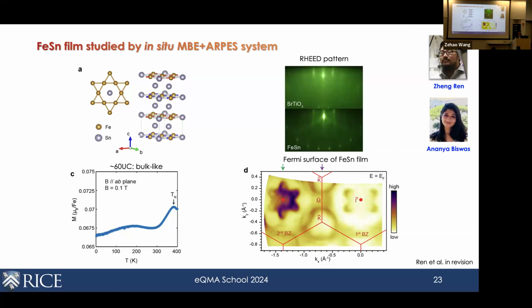So the really interesting or nice thing about this is that it turns out these thin films are very robust. They can live in vacuum for like a week, and you can still measure and everything is reproduced. And it's very robust also to thermal cycling. You can go across this TN and then come back down. And then to our delight, all of the features remain, which means that this is actually a really nice platform for answering the question, what happens across TN?